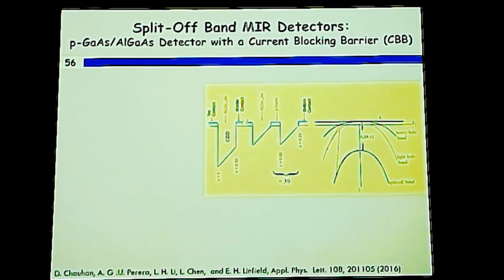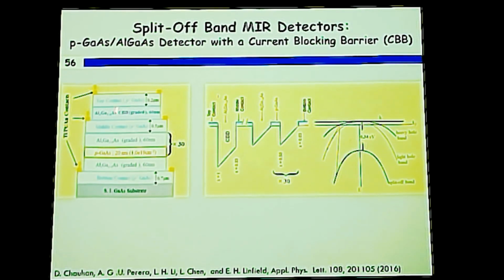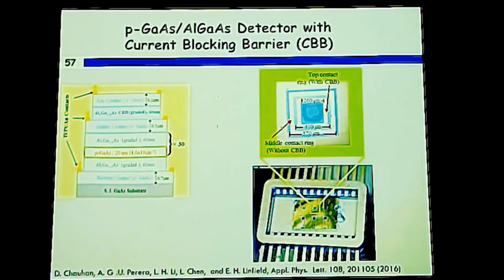Next, I'm going to show my continued work on the split-off band detector. These are also from the work I presented in my MS defense. So we used a blocking barrier on a regular 30 period heterostructure with graded barrier to operate at 0 bias. This is the heterostructure schematic, and there was a thick middle contact, and that was used to measure the response without the blocking barrier and with the blocking barrier on the same device to see the difference. And this is the processed mesa, top contact, middle contact, bottom contact.